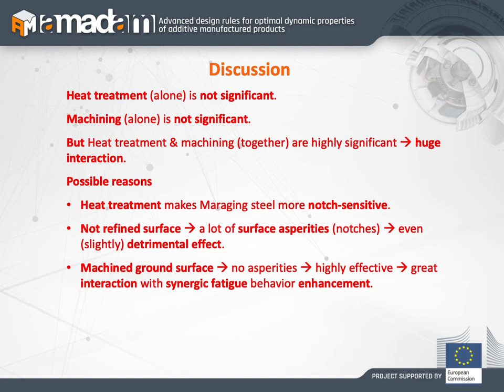So it is important to highlight that this treatment is always applied on the specimens, so it is able to reduce the porosity and the defects. So the only way to obtain an increase of the fatigue behavior, or the fatigue limit, is to combine together the two factors. So we have to apply the aging treatment and then machine the specimens.